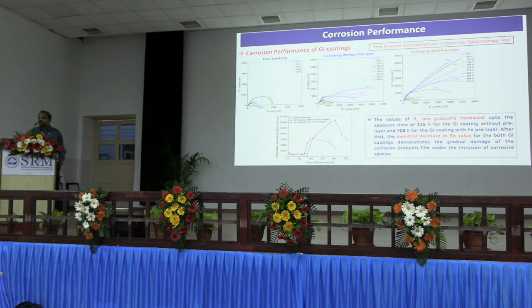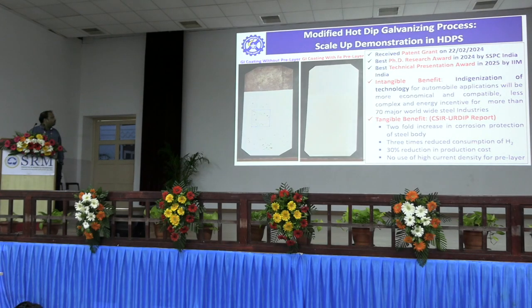So with respect to the corrosion performance, it showed good performance, which indicates good application for structural and automotive uses. We also further scaled up this technology from the small scale to a large-size DP980 steel sheet of 22 by 11 centimeters, and it showed very good mitigation of this galvanizability issue.